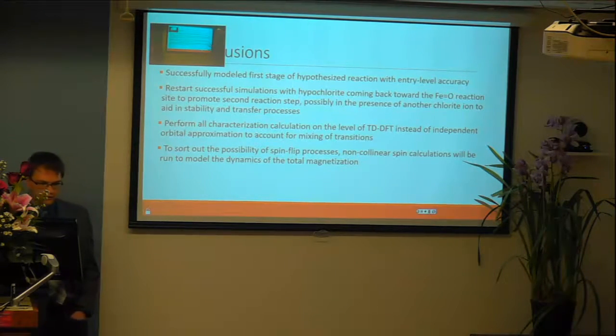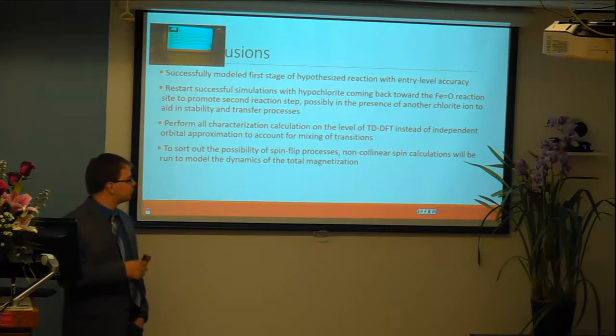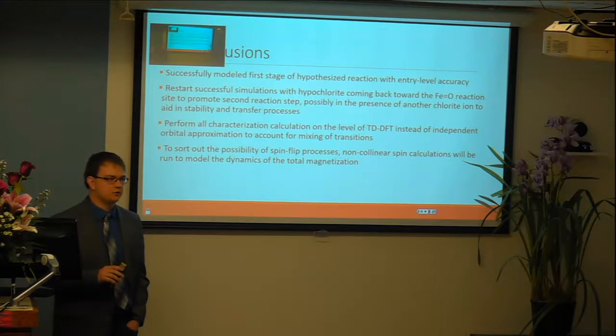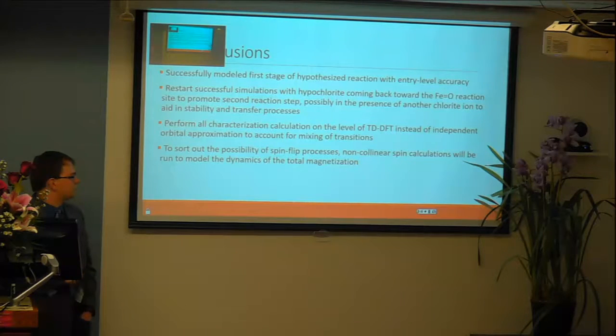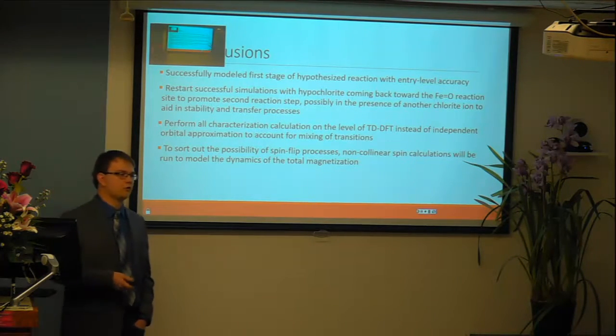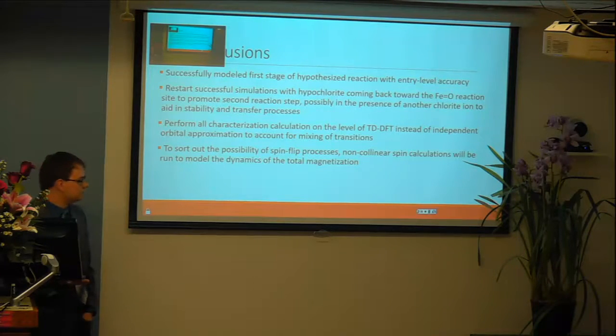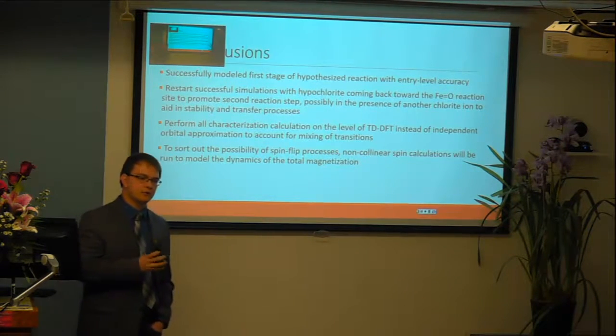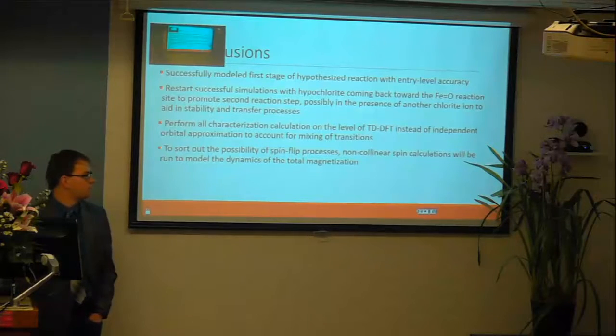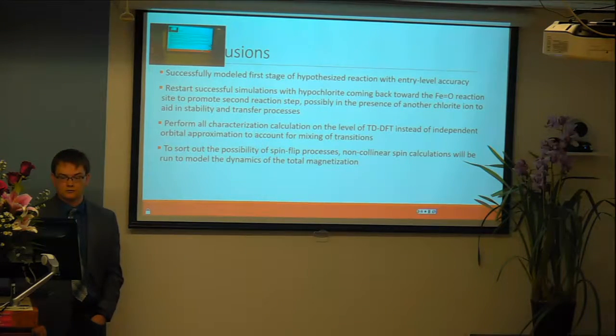To sort out the possibility of spin flip processes is also very interesting, and very interesting for this reaction, because in any transition metals, of course, you can go high spin, low spin. So you can use non-collinear spin calculations, which is much more expensive, but it allows for a time-dependent magnetization vector, which might be very interesting to look at as well.